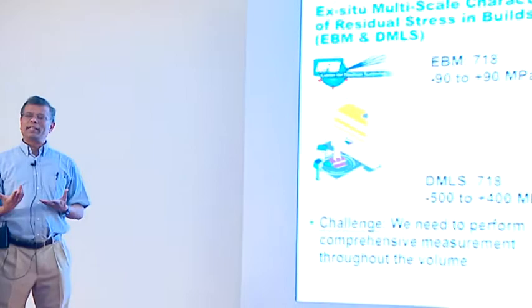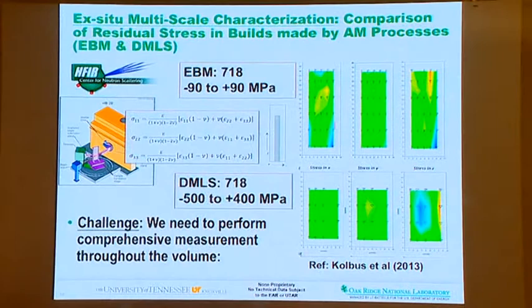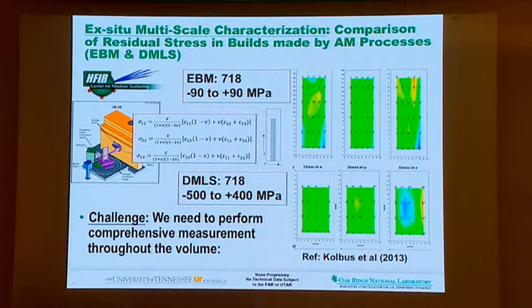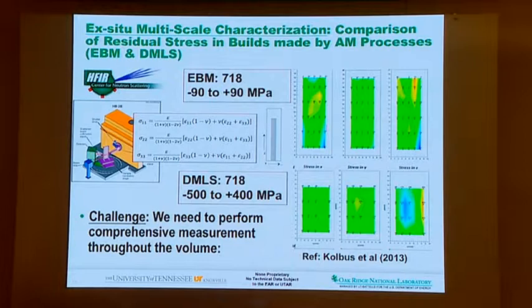Okay, now what is the next problem we have? Whenever you process welding or anything, you have what is called residual stress. When you heat up a material, you get a thermal stress. When you have a thermal stress, locally you initiate plastic deformation. Now you cool back down, and the plastic strain you created is not annulled, so it accumulates, and that accumulated plastic strain, and its gradient, gives you the residual stress. This is pure mechanics, and you see that happening during additive manufacturing. But you can make an influence on it.